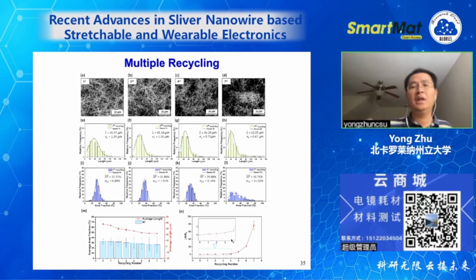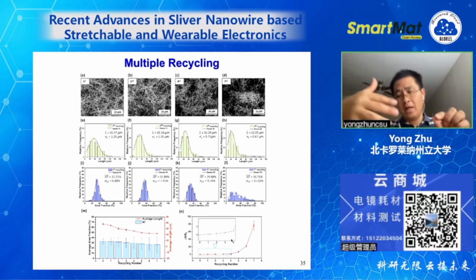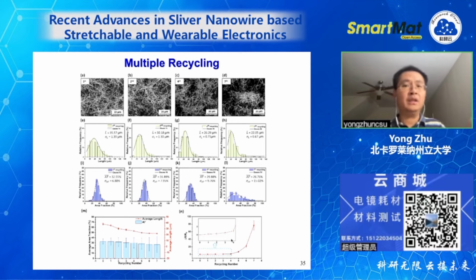And then we can recycle multiple times. With multiple cycles, both problems could occur. If you ultrasonicate multiple times, more nanowires will become shorter, and when they become shorter, the resistance will increase. Also the agglomeration issues can become more serious, because the working solvent is still the same. We use IPA in this case, but for silver nanowires you have a so-called PVP layer on the surface. If you wash it multiple times, that layer can get washed off, and that can lead to agglomeration. So anyway, we can do multiple cycles, but the quality could drop. I think we use about 4 cycles, and the resistance is reasonable, but after that the resistance increases quite a lot.